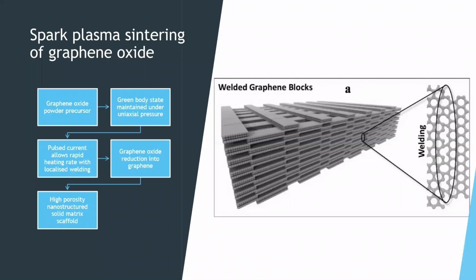In the process, the spark plasma sintering begins with the use of graphene oxide, preparing the material in a green body state, which is then maintained under uniaxial pressure. The spark plasma sintering allows the graphene flakes to undergo rapid heating and instantaneous localized welding due to the pulsed current. As a result, the reaction kinetics of the system reduce the graphene oxide into its pure graphene form, allowing a pure graphene nanostructure to be obtained.